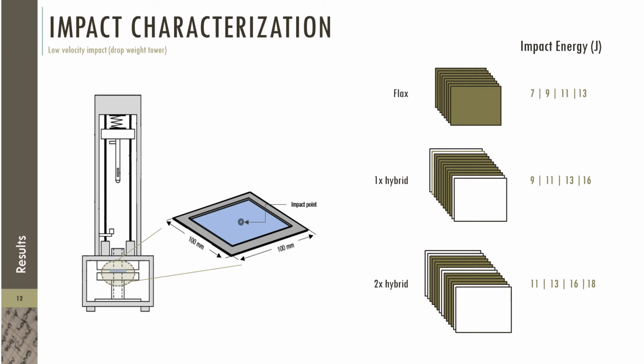For the impact characterization, we use a drop weight tower to perform a low velocity impact. Here we can see the scheme of the samples used in those tests and their dimensions. The impact tests were carried out considering not only the different kinds of composites but also the different impact energies.